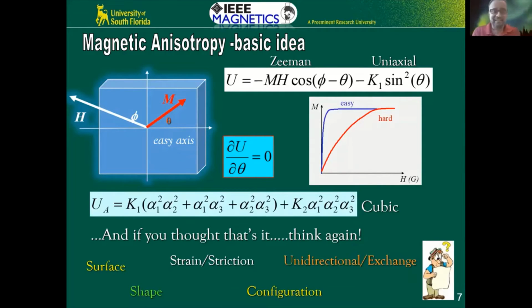The reason I say that is because in nanomaterials, it need not be just magnetic. It could be any kind of a nanoparticle. The surface atoms are the most important because they determine the configuration as well as the physical properties of the materials. So they are the most important, okay? So by manipulating the surface atoms in nanoparticles, we can effectively change the magnetic properties, certainly the anisotropy. So that's one thing that can contribute to this. Now shape, the second one, shape is easy to understand. For example, you can make nanotubes or nanowires, and obviously there is a preferred direction here.